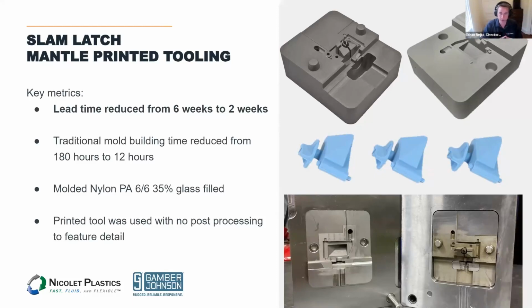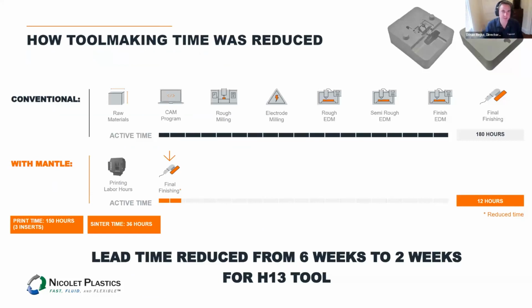They were molding thousands of these nylon 6.6 glass-filled components. The tool was used with no post-processing to feature detail. They were able to leave all that as printed with that D2 surface finish, because for this application, a matte surface finish was totally adequate. Looking at these charts again, you can see they're able to cut out really all the steps involved in this tool building process, except for that little bit of final finishing with the ejector pins and the fitting into the mold base, to go from 180 hours of their toolmaker's time down to just 12 hours, a lead time of 6 weeks down to just 2 weeks to produce H13 tooling.